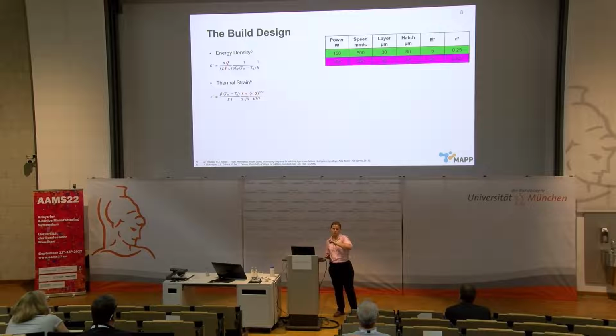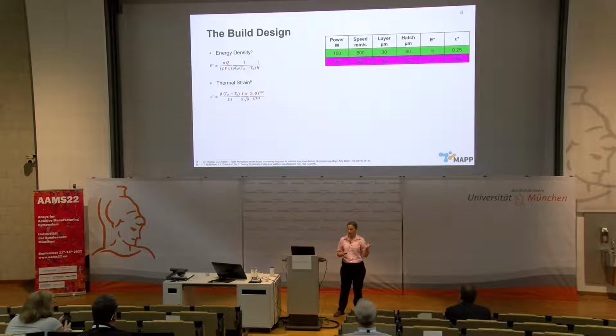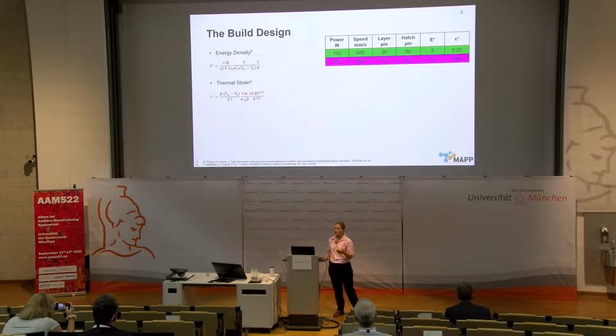There's a green one and a pink one. The green one is our low energy density parameter, so we can see a little lower on the power, a bit higher on the scan speed, and then the pink is our high energy density or high strain parameter, and we can see higher power and a much slower scan speed. What that gives us is a difference in energy density, but it also gives us a difference in strain.